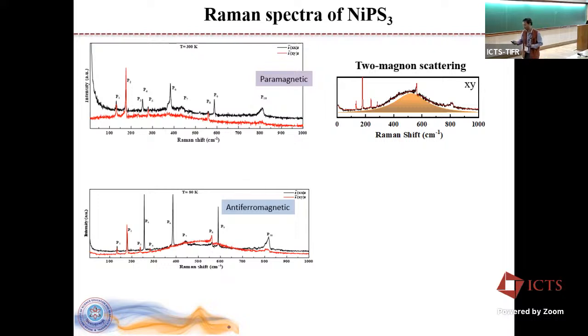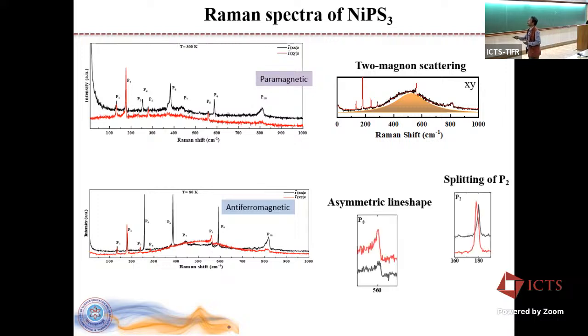One has to really think why. Okay, so these are the data, and what he saw was that if you remember this P2 peak, which was the signature for our antiferromagnetic ordering, that shows an asymmetric behavior. Interestingly, this asymmetric behavior is absent at very low temperatures. It starts to pop up somewhere around the antiferromagnetic ordering, and it becomes more important and vigorous at higher temperatures when it is not antiferromagnetic.